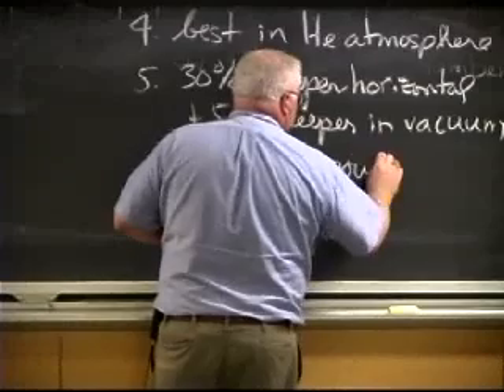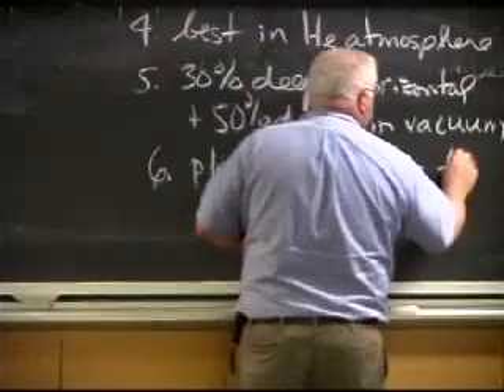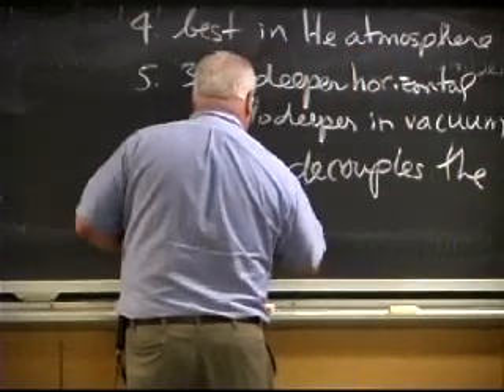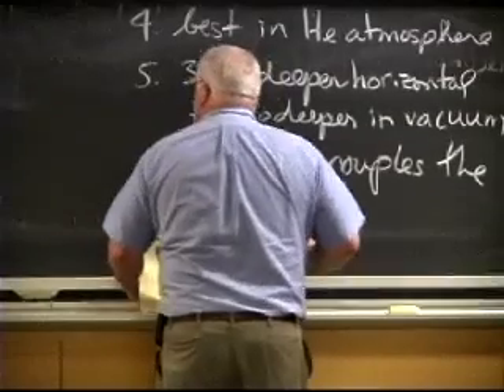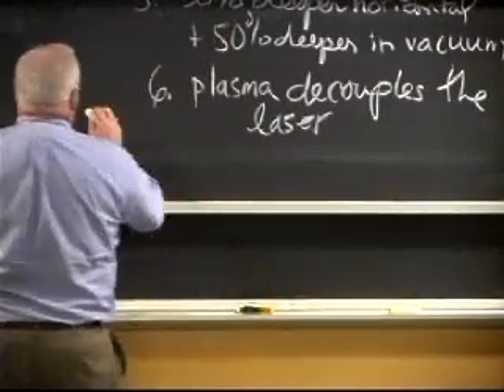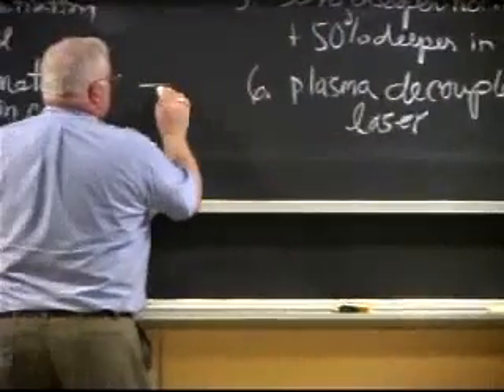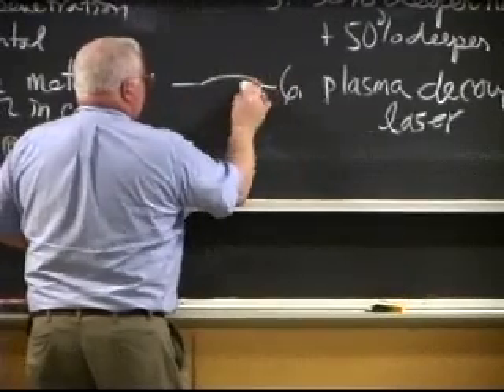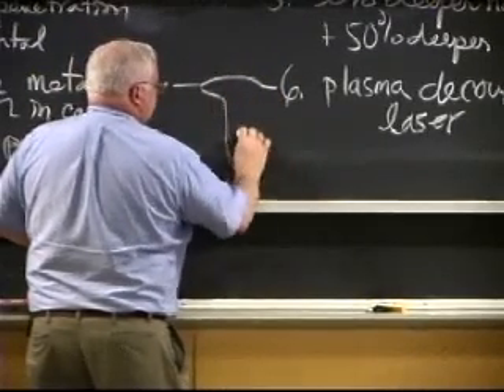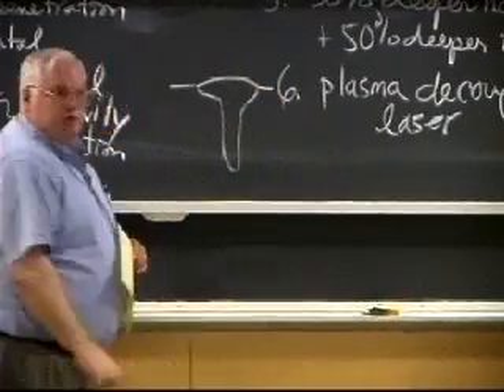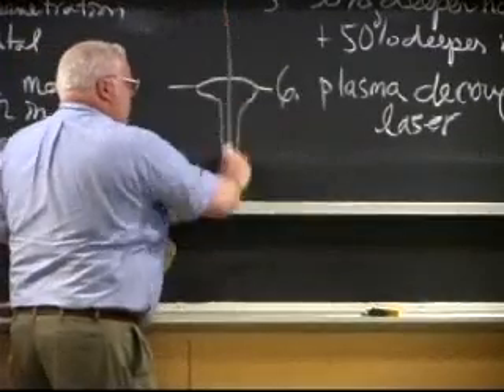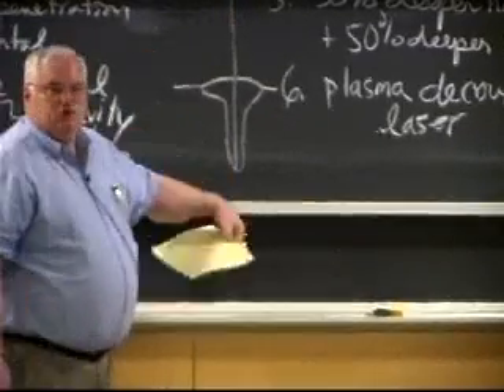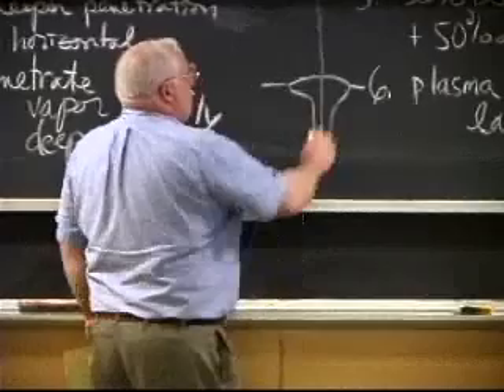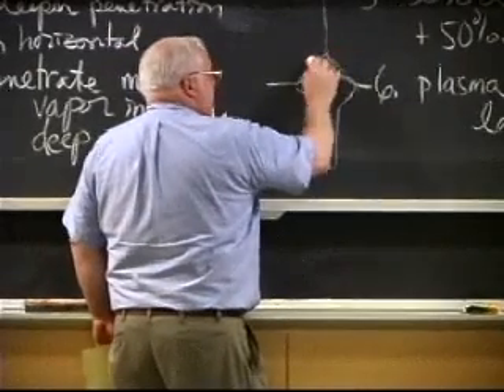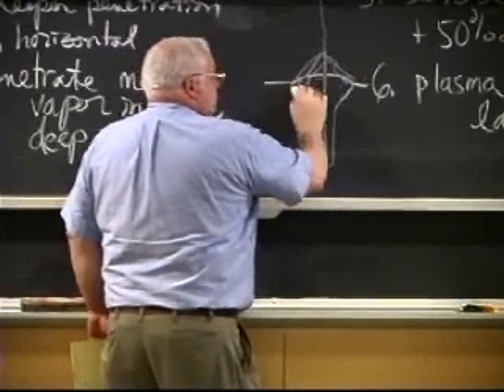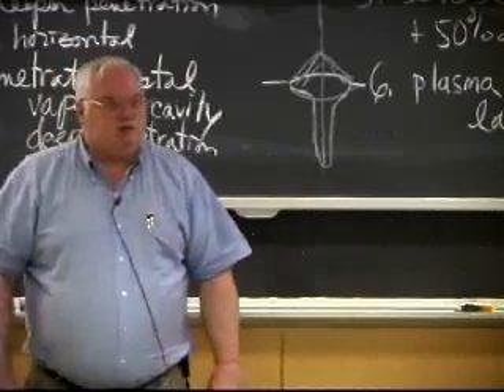And here, I just phrase it as plasma decouples the laser. And as it decouples the laser, both with electron beam and laser, this decoupling on the surface will produce what we call a nail head weld pool. You'll get this with both electron beam and laser. Part of your main beam is coming down and is drilling that hole to the bottom, but some of it is defocusing up here in the vapor. And as it defocuses, you basically melt the surface and get a nail head.